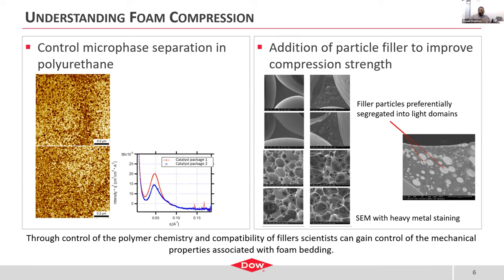Additionally, when we think about the viscoelastic effect, the way that we typically generate something that is more viscoelastic or has more of that memory foam feel is by making it softer. There's typically a linear correlation between softness and viscoelastic effect in the polyurethane system. Now, you can think, if you want a memory foam mattress or a mattress that has that nice viscoelastic effect, but you, for instance, like a firmer mattress, you could see where there's a difficulty there, where in order to get that viscoelastic effect, you need to have a softer polymer, but you want that firm mattress.